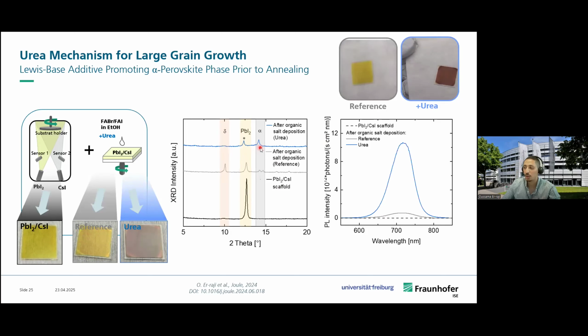So having these different measurements in mind, we hypothesize that the ability to form the alpha perovskite phase prior to the annealing gives us the chance to have crystal growth and nucleation before the annealing step. So we already form seeds, which then lead to the growth of larger grains during the annealing step. So this is with regard to the crystallization change. What about the change on the interface?